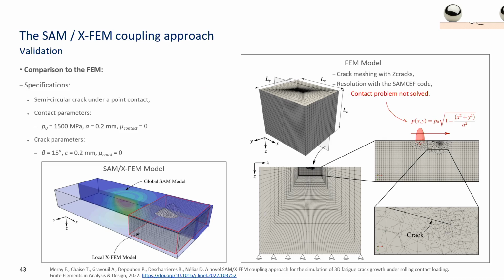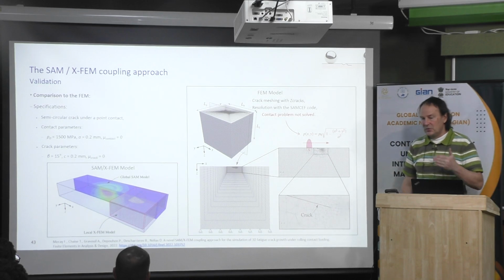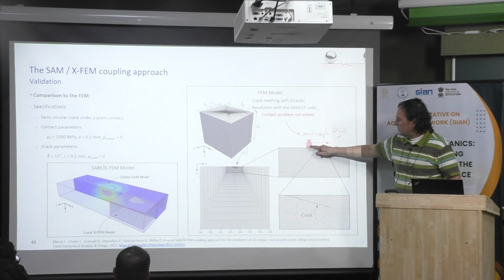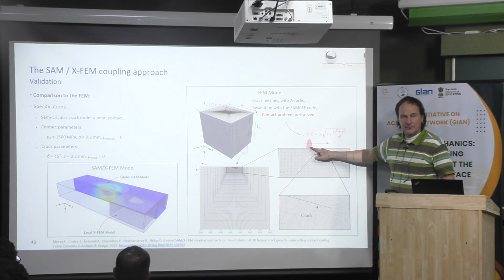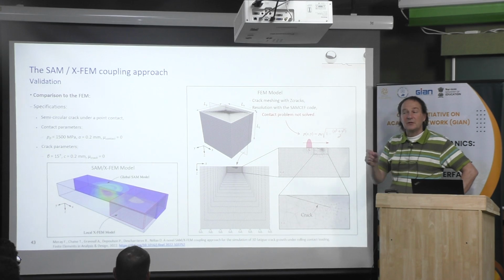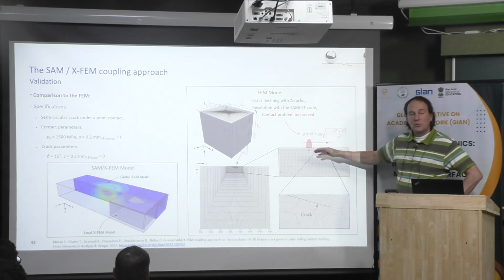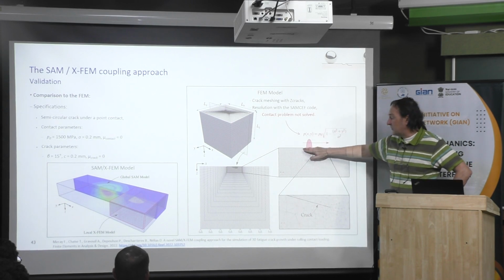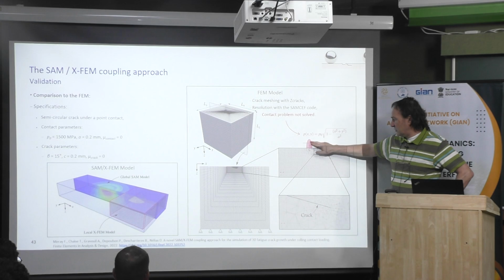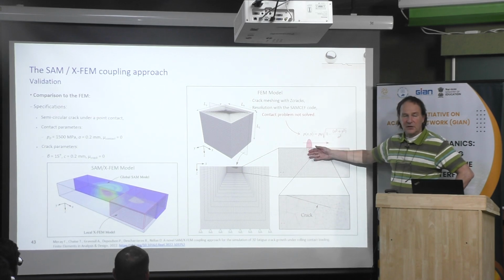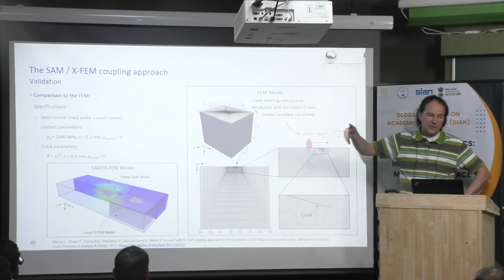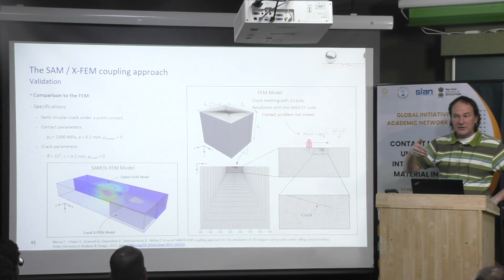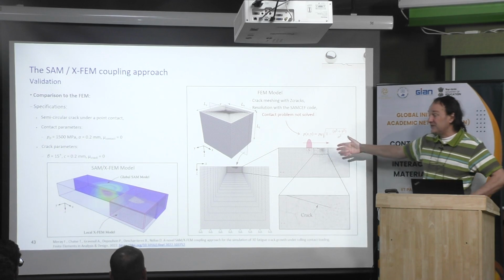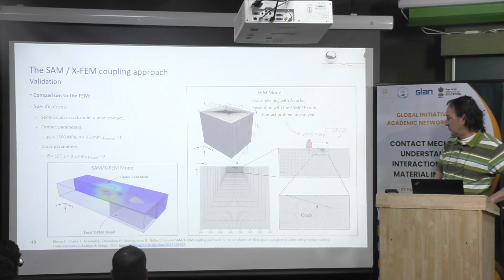Then this is an example of the problem. Also something which is different from the literature. In the literature, sometimes you can find some similar work, but very often they just assume Hertzian pressure distribution, and there is no contact involved in that. Here, we are able to solve the contact. I mean, if there is some surface defect, the pressure distribution is perturbed by the defect, and we can account for that. And because the SAM method is very efficient or fast in terms of computing time, it costs nothing, in fact. But when you use only a finite element method, it can be complicated to do that properly.